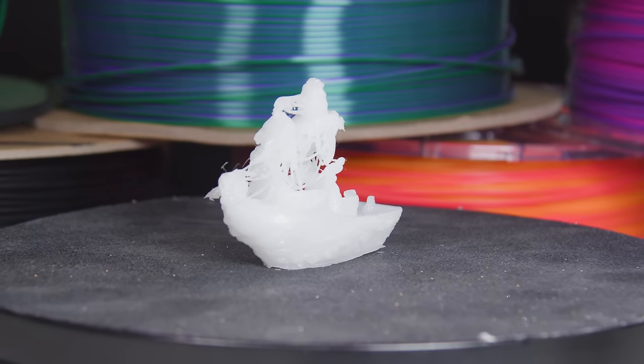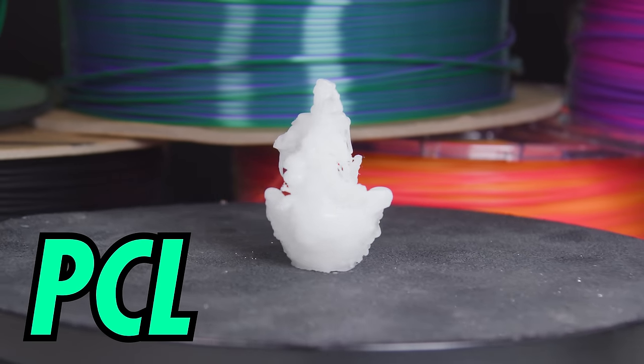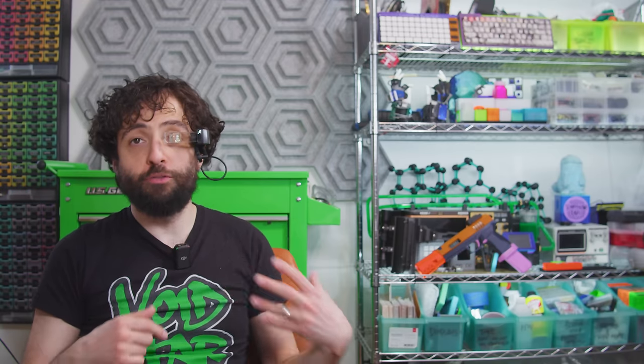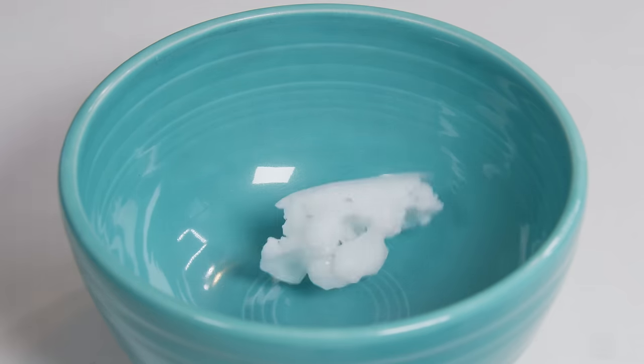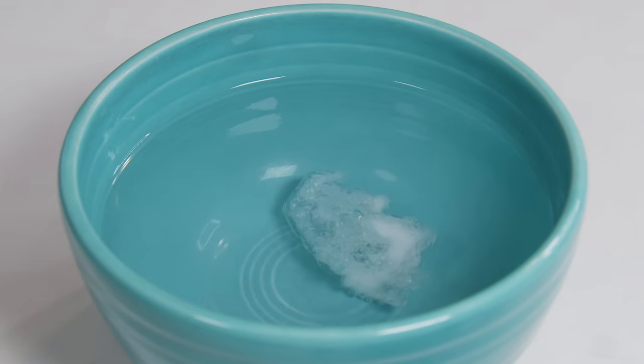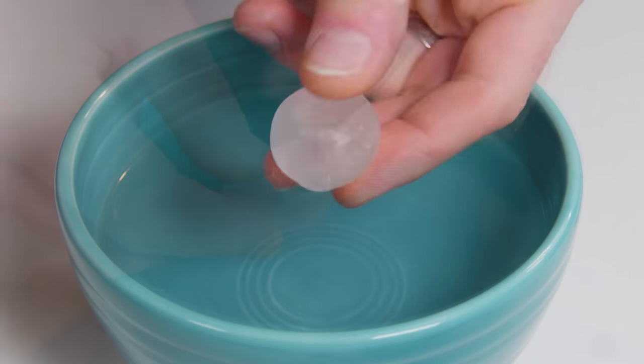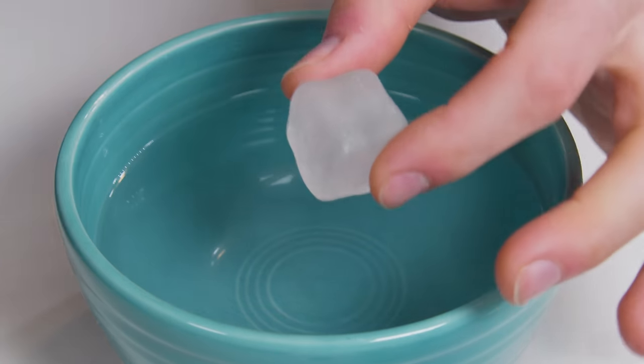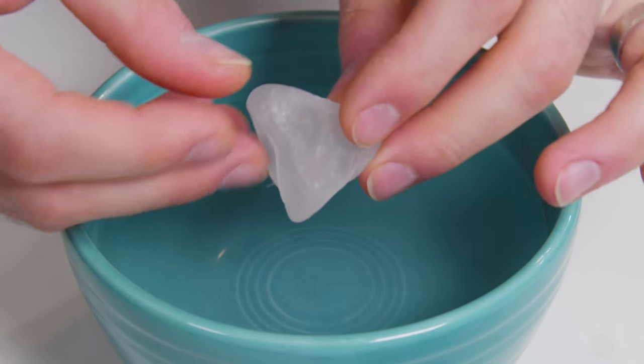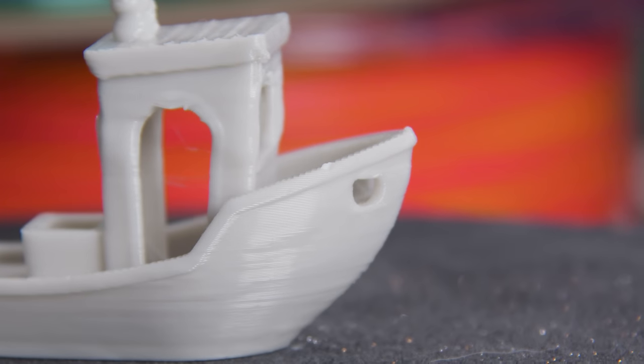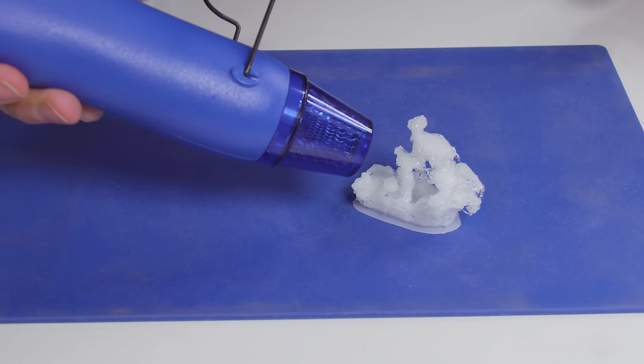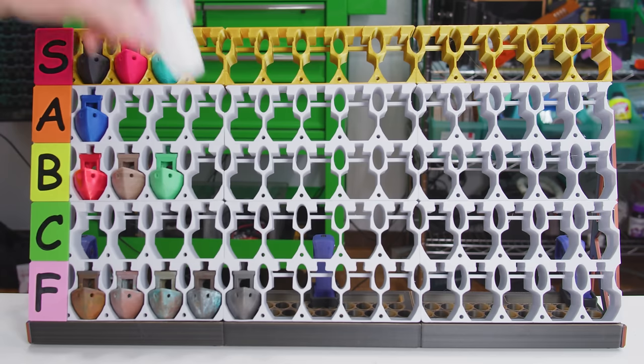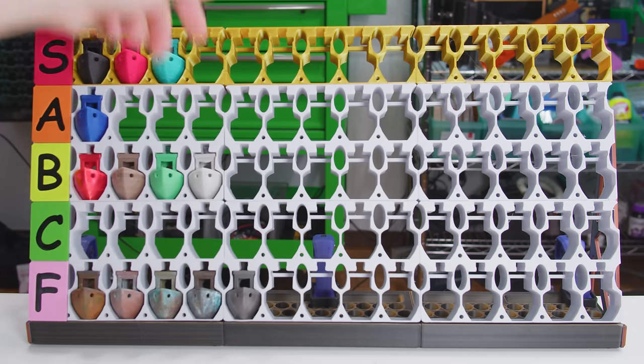I'm including this for historical reasons, because flex PLA has nothing to do with PLA. It's MakerBot's inexplicable brand name for polycaprolactone. This stuff doesn't normally look this crappy. This sample was donated by Ren from our Discord after sitting in their closet for like nine years. PCL is the second lowest temperature material on this list. It prints at only 100 Celsius and softens in a warm bath. This stuff has a translucent, waxy consistency that no adhesive will ever stick to. In fact, you can use PCL as an adhesive. ShapeLock, Instamorph, and other sculptable plastics are just pellets of PCL. This filament is particularly useful for prosthetics, because you can use a hair dryer to contour a model to fit the wearer even while they're still wearing it. PCL's ridiculous low temperatures can be genuinely hard to print, but I'm still gonna put it in B tier, because where it's good, it's downright life-changing.